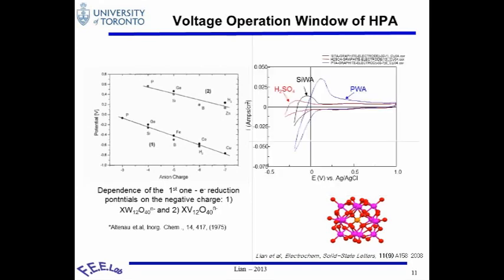Let me show you some of the graphs we've done in the lab. In this case, we started with sulfuric acid, which is a standard, well-known electrolyte. By looking at the phosphotungstic acid and the silicotungstic acid, you see the first reaction voltage window has been pushed towards the negative range. Then when you look here, the black and the red, which is phosphotungstic acid, sulfuric acid, and the SiWA, are very, very similar.